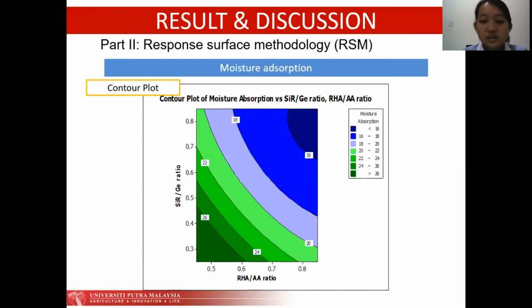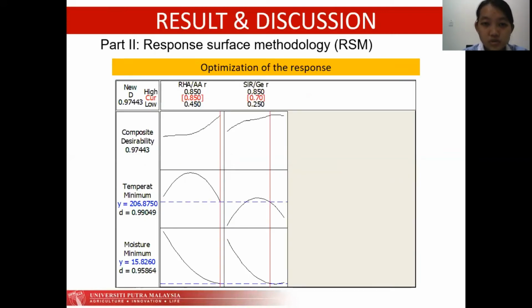Besides, the interaction between the nanoparticles, which is the silicon in the RHA and the silicone rubber, leads to an increase in physical and chemical cross-linking points, which are likely to contribute to the improvement of thermal stability and also resistance to moisture. In addition, the silicone rubber has good hydrophobicity and can also improve the resistance to moisture. So this is the optimal composition of both ratios that can achieve the best moisture resistance and fire retardant properties of the coating.